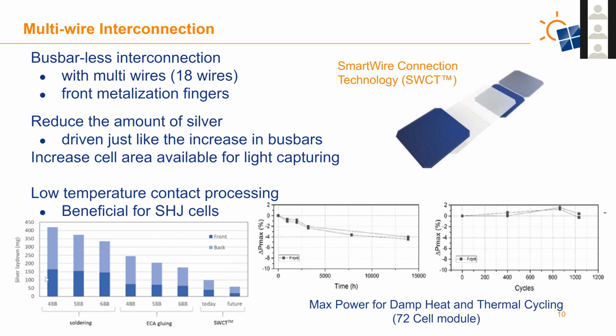This bottom figure shows that as we go from 4 bus bars to 6 bus bars with typical soldering, we reduce the amount of silver laid down. We'll talk next about electrically conductive adhesives, which also reduce the amount of silver used compared to typical screen printing. And these multi-wire interconnections have much less silver still.